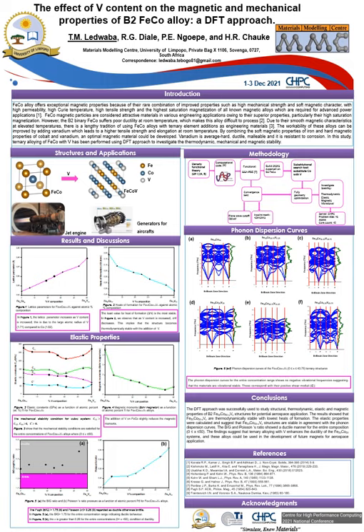To put the cherry on top, we have determined the phonon spectra to check vibrational properties, and it is clear that all the systems are vibrationally stable, which means our materials will not break easily or vibrate excessively. In conclusion, we are happy to say that vanadium is recommended as a ternary element for the B2 iron cobalt system to improve ductility.